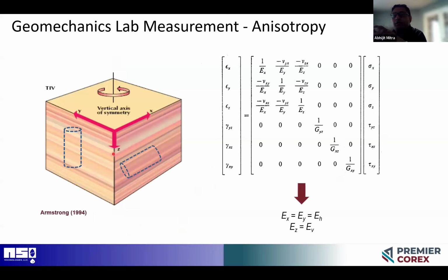Now, if we go to the next slide, this cartoon on the left tells you that our caprocks are mostly anisotropic, and we use the TIV anisotropic model. So we take one plug perpendicular to the lamination and the other one parallel to the lamination to conduct our triaxial compressive strength measurement. And on the right, you can ignore this, but some of you already know, this is the anisotropic stiffness tensor. This is where the EH and EV, the Young's modulus perpendicular and parallel to the bedding, come into play, and that's what we try to estimate.